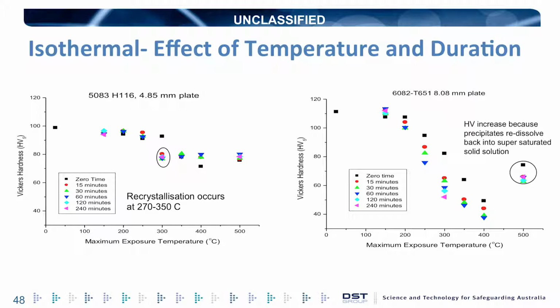In this 5083, you can see we're getting a 20% reduction if we have a fire between 300 and 500 degrees for even 15 minutes, up to 240 minutes. And again, with the 6082, there's a much larger drop in the hardness values over those temperature ranges. And if hardness is related to strength, and we have a fire of one of these magnitudes, then the strength of the ship structure is going to change.